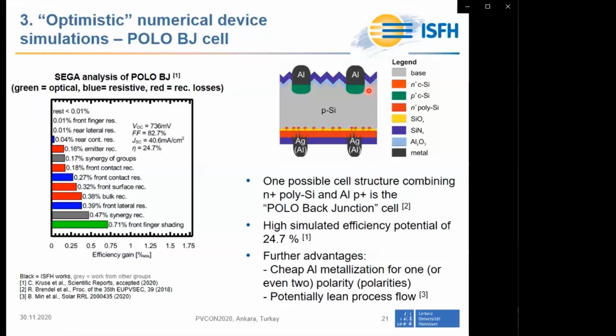It features aluminum fingers on the front side, just like the rear side of a PERC cell. The simulated efficiency potential, according to our numerical device simulations, is 24.7%. This is lower than our selectivity limit of 27% for this contact combination, and the reason for this difference is that we here include all relevant extrinsic losses. Nevertheless, this efficiency potential is quite high, and it's significantly higher than that for the PERC benchmark.